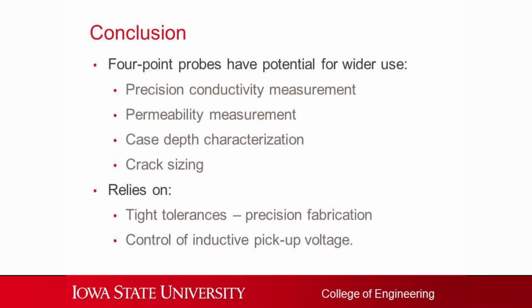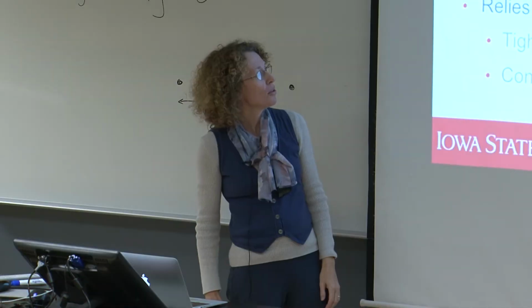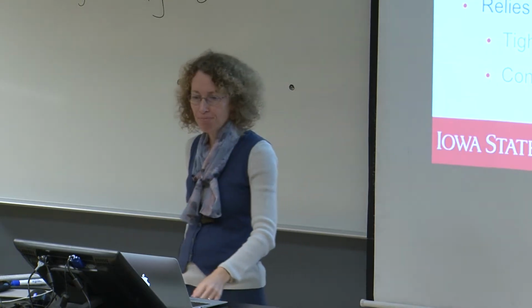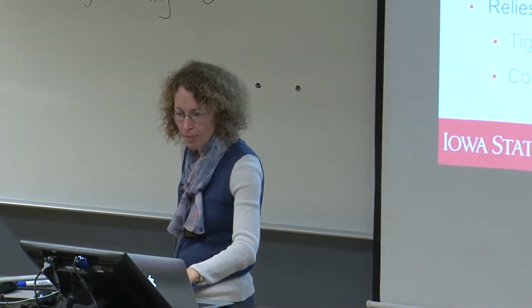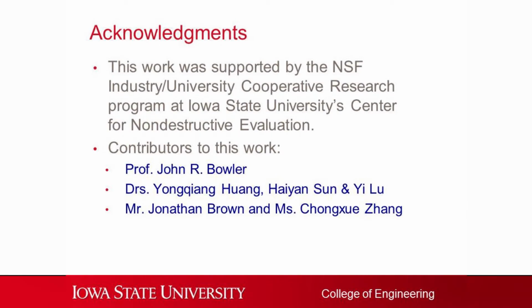So maybe that's something new for you, this 4-point probe technology. We can precisely measure conductivity, and can also measure permeability if we use higher frequencies. We can characterize the depth of hardening, and I didn't talk about it, but we can size cracks as well using this. These are just a few people who helped out with this work in the past. So that was my first part here.